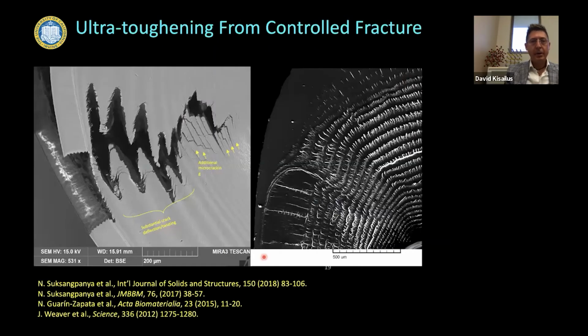And you can actually see what happens upon impact. This is actually from another region of the mantis that also has a helicoid structure. It's actually its tail segment called the telson that also has a helicoid structure, but you can actually see crack deflection and crack twisting. In the club itself, we've actually sectioned the club after we didn't count. There was no one there with a clicker counting how many impacts it had, but it was mid-molt. And we basically determined by letting the electron beam sit on the sample, this secondary charge contrast imaging, that the club is actually riddled with damage, but none of the cracks have managed to actually propagate out of the club.